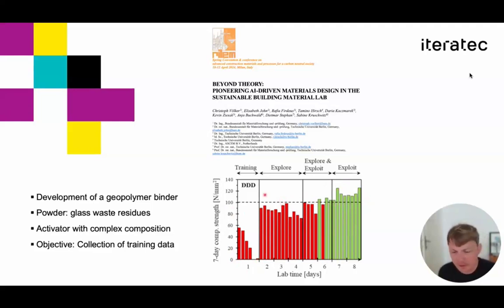So the design assistant would come in here at the very beginning, where we didn't have any training data and made a rather poor choice in the initial data set. So the question is, if we would have collected better data, would we have ended up with these high performance materials much, much quicker? And the design task specifically was based on a powder from glass waste residues. And we wanted to design an activator liquid with a complex composition where some of the compounds were substituted with cheaper byproducts from industry. And the objective in the initial round was to collect training data, which means the data should cover some of the variability within our design space.